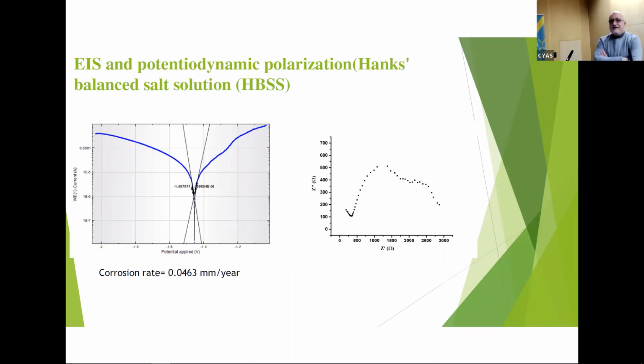That's called potentiodynamic polarization or electrochemical impedance. It's a little bit complicated, but that gives indications about the resistance of your coat. And this type of equipment also gives you indications about the corrosion rate. For the corrosion rate, we have to make some kind of tangent on this polarization, and that's the impedance. The right one is the impedance. There are 2 peaks, and that gives indications about how big the resistance of your coat is. That's a little bit complicated. Here it gives you indications about the corrosion rate, which reaches about 0.04 millimeter per year.